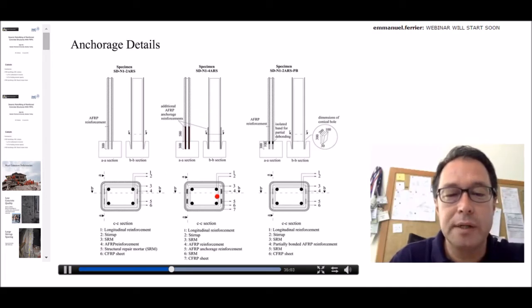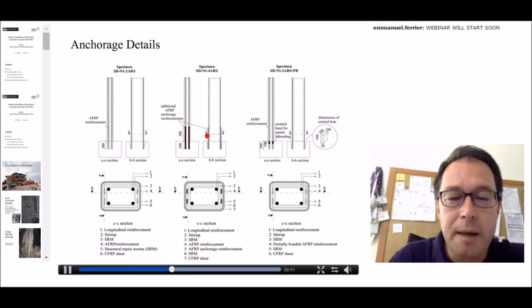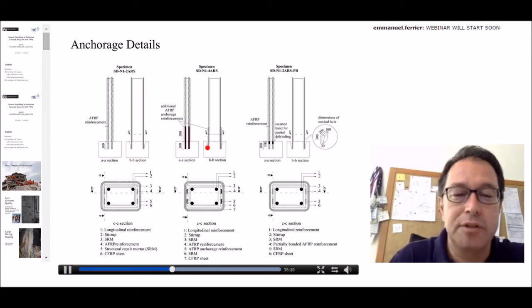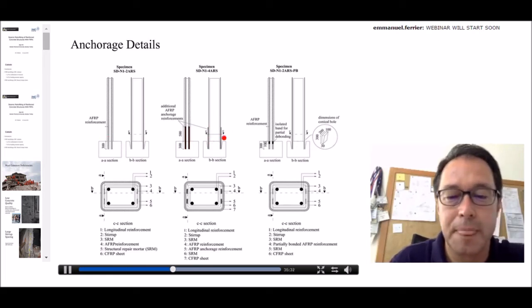The next specimen here, as you see, has those 4 AFRP bars like the previous one. But in addition, we have some additional bars which are used for only anchoring purposes. Of course, nevertheless, they will have some contribution to flexural capacity as well. But the target is to avoid some anchorage failure at around this zone. But this solution is a little bit more costly with respect to this one.